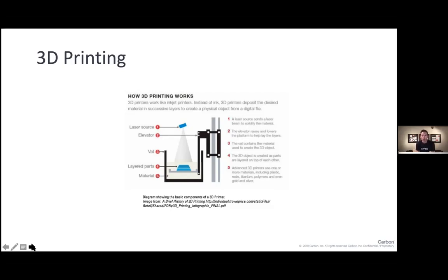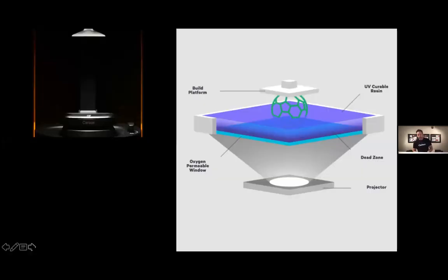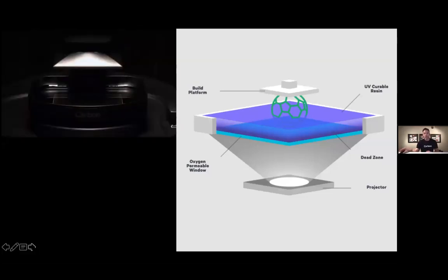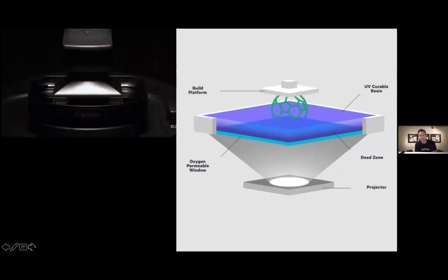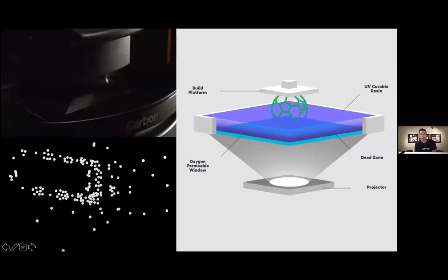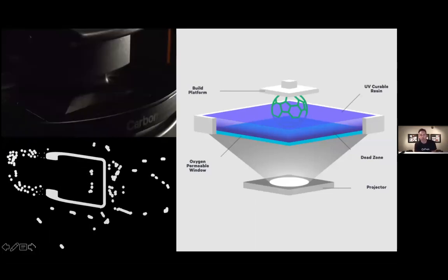It's also yielded parts that are rough, and I think of them like a wafer cookie. They're not as strong, and they have different mechanical properties because of the way that they're built. But the co-founders of Carbon realized that while the UV light will cure the resin or partially cure it, oxygen inhibits that curing of the resin.